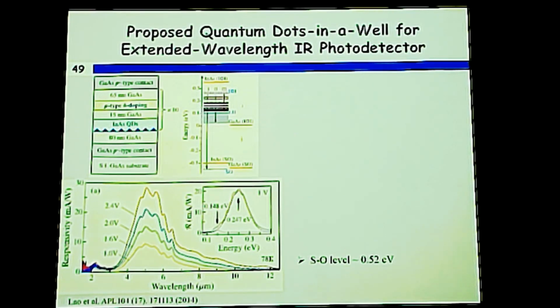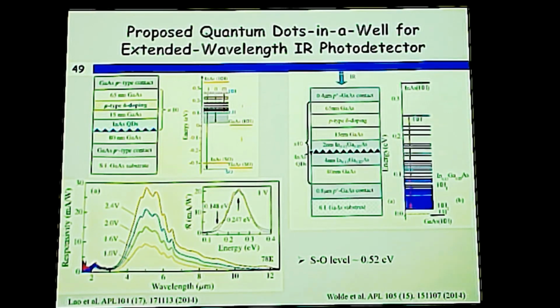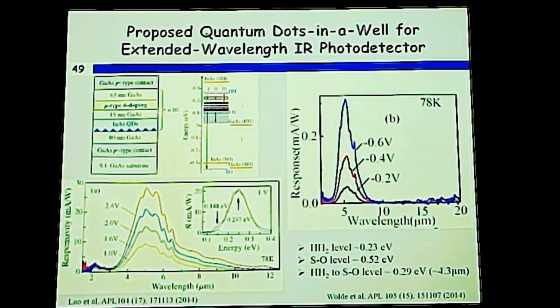To get to that, let's look at another device, a quantum dot in a well. Similar quantum dots, but now in a 6 nanometer well. So there are additional energy levels, heavy hole 1, heavy hole 2, and again there is this barrier edge. Close to the barrier edge there is a transition, and based on this transition the energy level is about 0.23 electron volt, which is close to 5 micron, and there was a peak close to 5 micron absorbed. So there was this transition.